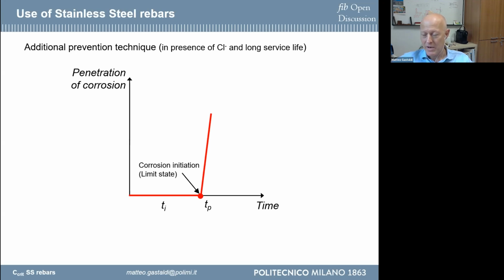As Professor Marquez showed before, there is a problem related to the concrete cover that you need to guarantee the passive condition of steel rebar. For a structure with 50 years, that is higher than 70 millimeters. This is not feasible because the problem is related to cracking of the concrete cover, and if you consider 100 years of service life, the problem is higher. And so for this reason you have to consider another solution, and the use of stainless steel rebar can give you the answer.